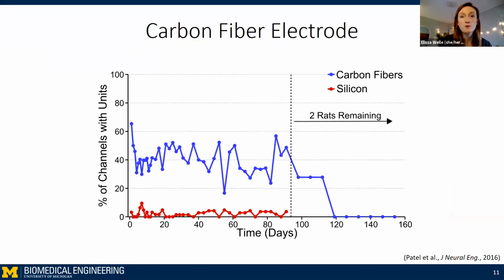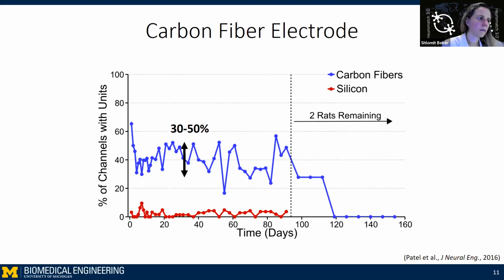And we noticed that when we implanted these chronically, when we implanted functional electrodes, even though their impedance remained really good, we are actually only recording from roughly 30 to 50% of our functional electrodes in the brain. So we implanted them and only 30 to 50% of the functional electrodes recorded any neural units. This was confusing because despite the good histology and the low impedance, we're only getting about a third of our electrodes actually recording spikes, which is obviously the point of what our electrodes are for. So, in order to use these in future brain-machine interfaces, we want to increase this recording yield to hopefully 100%.